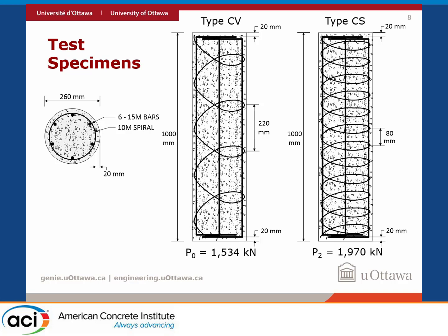Now, the materials used had a high water cement ratio because we wanted to achieve corrosion damage in a shorter period of time, within 10 months. So the water cement ratio was 0.6. I realize this is a little bit higher than what would be required today for this type of element exposed to a chloride environment. We also mixed 3% of sodium chloride into the mixing water to accelerate and trigger the corrosion process. The average 28-day compressive strength of concrete cylinders cast at the same time was 27 megapascals. The yield strength of both the longitudinal and spiral reinforcement was 400 megapascals.